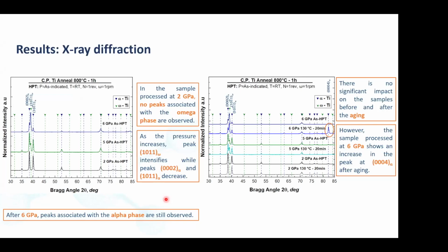So in general, when we increase the pressure, in the case of this study, we didn't see the omega phase with 2 gigapascals, but when we increased, for example, to 5, and we did this like 3, 4, 5, and 6, and then we went somewhere between 5 and 6, 5.2, 5.4, and with this sort of analysis, we discovered the change in the fraction. And you can see the peak of the omega phase here increasing at the expense of the alpha phase. And also we tried aging, and seeing how the aging will change the stability of the omega phase.